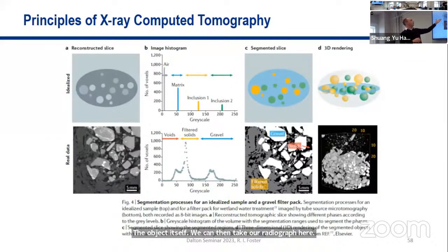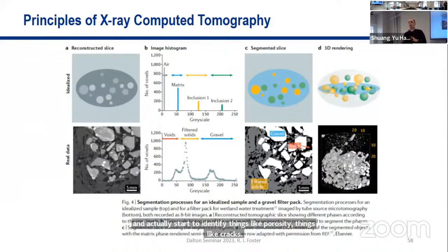We can then take our radiographs and do what we call segmentation, where we identify and allocate each of the voxels, each of the 3D pixels, to different materials based on their radiograph properties or density or other measures. And then we can analyze our materials. So for example, here, you could say that you've got gravel, voids, and filler solids on a concrete sample or a geopolymer sample, and start to identify things like porosity, cracks, voids and things like that, which for long-term storage is quite important.